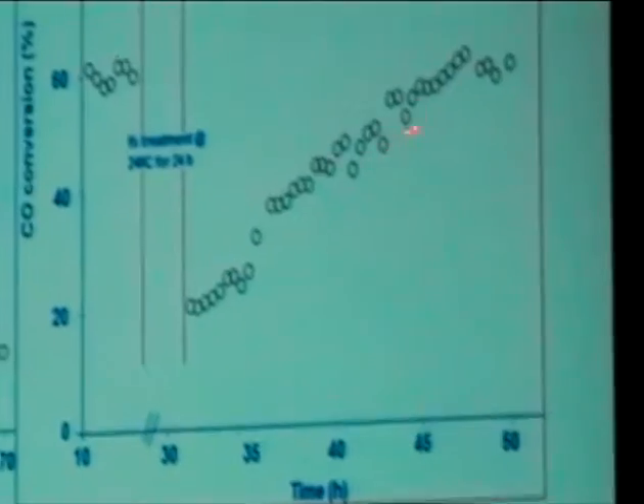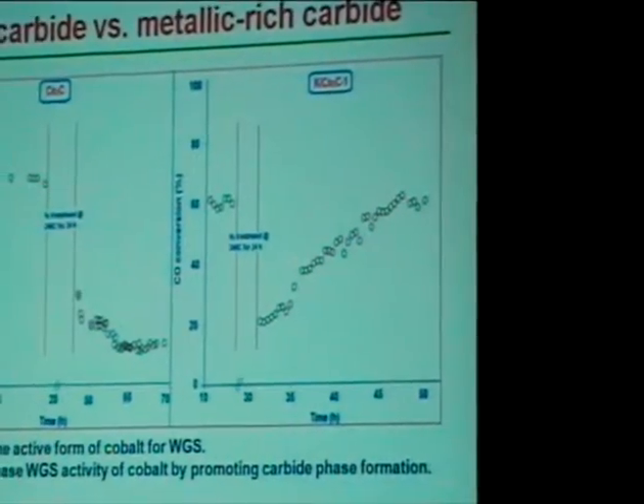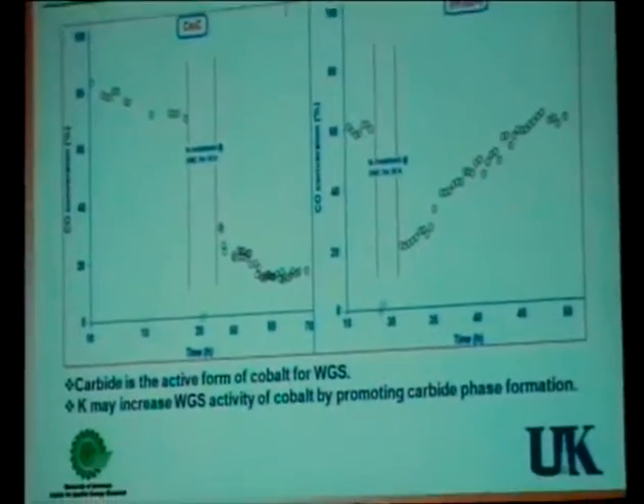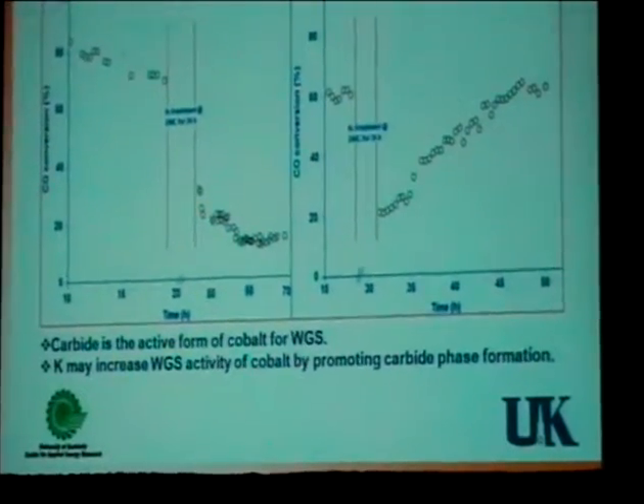It means it could be because carbon builds up as the run progresses, and it makes again the carbide phase by the promotion effect of the potassium. So this indirectly indicates that the cobalt carbide could be stabilized in the presence of potassium under the water gas shift condition, which ultimately increases your water gas shift activity. So potassium is essential for the cobalt carbide for the low temperature water gas shift applications.